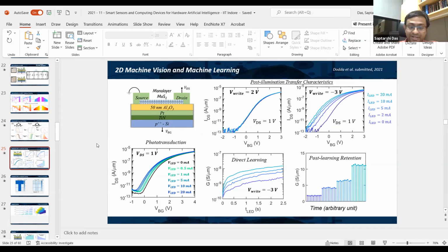It shows that it can be done, but in order to scale it up, we need to make sure that we have degenerate doping of this 2D material. That's what we are working on with my colleagues, to see how we can degenerately dope these 2D materials under the contact area. That will be the ultimate rescue for the contact resistance problem. Yeah, there are some reports that they expose it to argon plasma and form it into a metallic state, and that probably can do it.